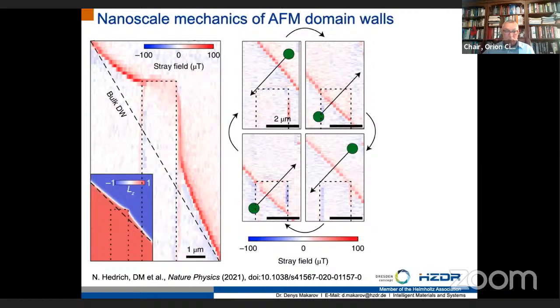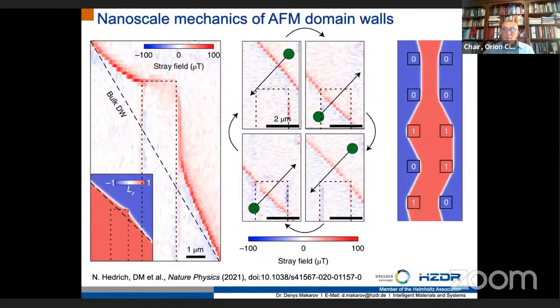In this case, what you can tell about the mechanics of magnetic domain wall in chromium oxide is that it resembles something similar to elastic ribbons. That would be an appropriate model for how you can understand the behavior of the magnetic domain walls in this material. What is interesting is that you can use the laser beam in order to manipulate the position of the domain wall, achieving the stable pinning on one edge of the meso or on another edge of the meso, which enables an interesting possibility to even consider such kind of elastic domain wall in a material as a possibility to write information by following how the domain wall follows the mesostructures which are patterned on the surface of the chromium oxide single crystalline material.